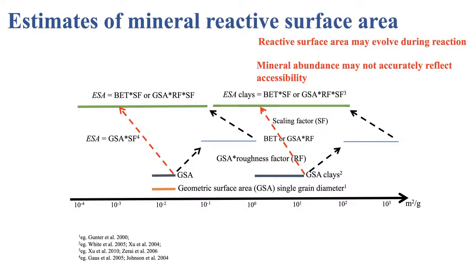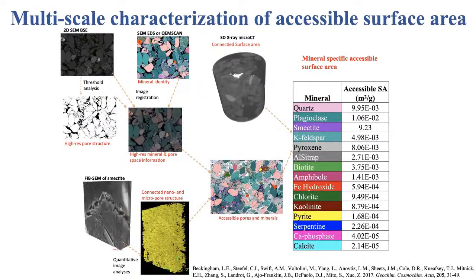In recent collaborative work, we used a multi-scale imaging approach to actually quantify the surfaces of minerals that would be accessible for reaction. So we combined 2D SEM imaging with high-resolution FIB-SEM imaging to look at the nanopore structure of clays. We can account for connectivity in 3 dimensions through CT imaging and actually quantify mineral-specific accessible surface areas.